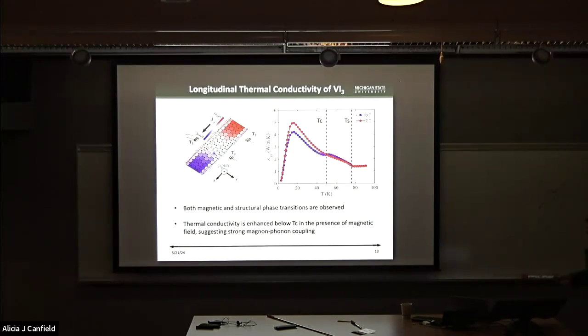Could you comment a little bit on the setup? So you're measuring voltage between these two, you're measuring what exactly? So you have a thermal gradient along X, but you're measuring the voltage. Yeah, so this is the schematic of the setup. We put a heater here, we heat up this end, and here is the heat sink. We attach the sample to the heat sink directly. And then we put three sensors, T1, T2, T3, and then we measure the temperature directly. There's no current flow anywhere, and this is an insulating compound, but also everything is floating. Yes, everything is floating.